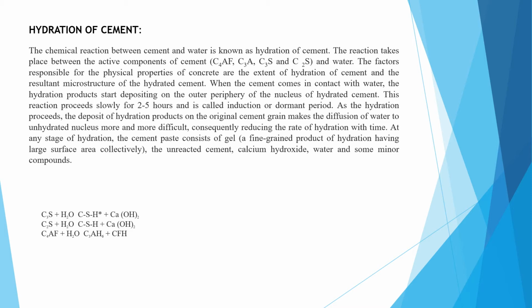Now, this is the most important topic of cement: heat of hydration. The chemical reaction between cement and water is known as hydration of cement. The reaction takes place between the active components of cement, C4AF, C3A, C3S and C2S, and water. The factors responsible for the physical properties of concrete are the extent of hydration of cement and the resultant microstructure of hydrated cement. When the cement comes in contact with water, the hydration products start to deposit on the outer periphery of the nucleus of hydrated cement.